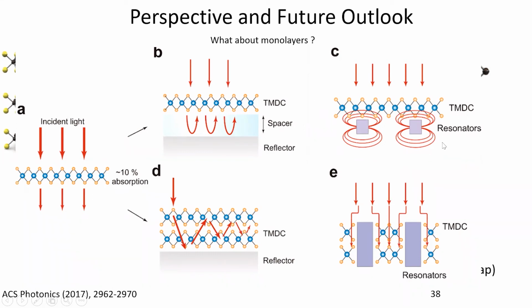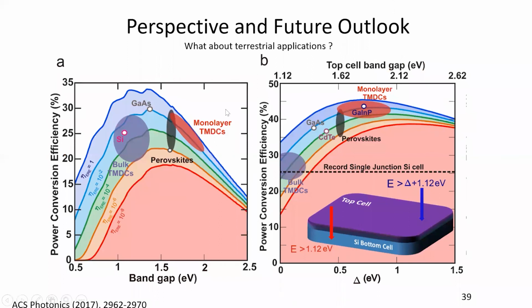And the good news is, in the last couple of years, people have already published in these areas where people have shown very high light trapping in monolayers. And even we are working on some of these results that we'll publish in the coming year. And so I don't think light trapping in monolayers should be a problem moving forward. The advantage that you get from monolayers is clear, because they are direct band gap and they have higher external radiative efficiency, they can be much closer to the ideal limit. Okay, and therefore they can occupy the space over here.